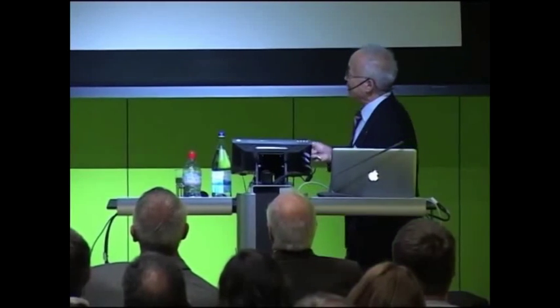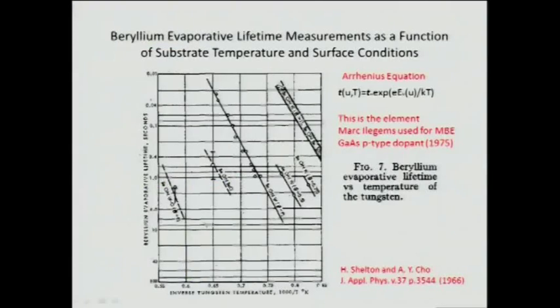With that, we plot the logarithm of time as a function of temperature, 1,000 over degrees K, on a semi-log plot. This is a so-called Arrhenius equation plot. With that, we can find the activation energy for different elements. In this particular case, it is the evaporative lifetime measurement as a function of the substrate temperature and the different conditions of the substrate. And in fact, this element, beryllium, was first used by Marc Ilegems, who is also in this audience, for the demonstration of MBE, as a very important p-type dopant for gallium arsenide in 1975.